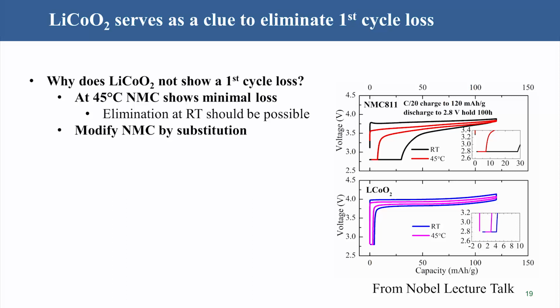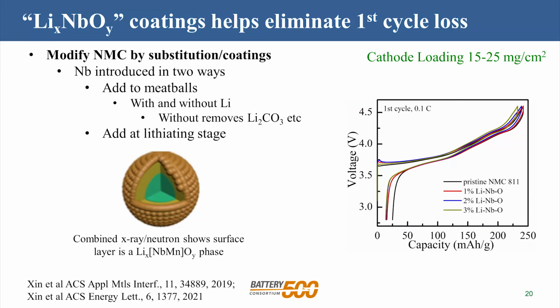And you can see the black curve there is room temperature. If we held it there for 100 hours, all lithium goes in. If we raise the temperature, then the red curve there at 45, most of it goes in without that need to hold. Lithium cobalt oxide, it all goes in straight away. So we said, let's modify our NMC by substitution or coating, and we did this using various lithium niobium oxide films. Lithium niobium oxide is known to be a reasonably good lithium ion conductor, so we coated the entire surface, the lithium could still go through it.